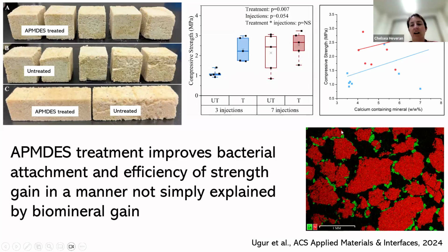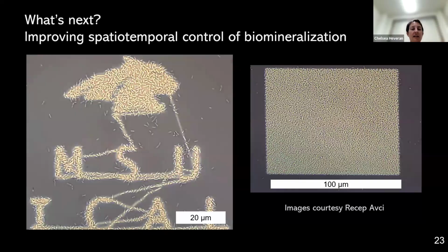One thing that we found that I found really interesting is that these calcium carbonate bridges, here seen in green on our SEM EDX map, have a different shape and size with our treatment. So we think there are changes to how biomineral nucleates and grows on our treated surfaces, and we're working to understand that more. Okay, so what's next for us in this space? Well, we're trying to, again, improve how we pattern microbes on surfaces so we have better control over where we biomineralize and where we don't.